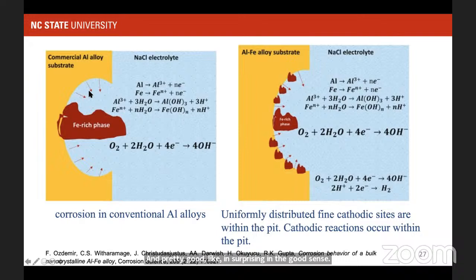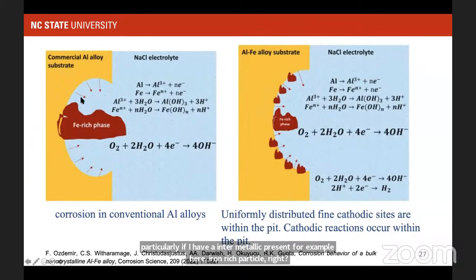So one thing we learned from that work, which would be applicable for a lot of alloy development, is that conventionally, in aluminum alloys particularly, if I have an intermetallic present, for example here an iron rich particle, it could be a constituent particle, it could be an inclusion, that serves as a local cathode, and everything else around